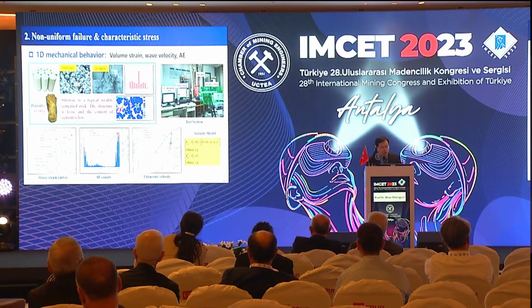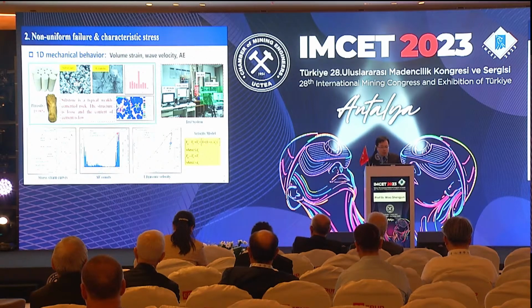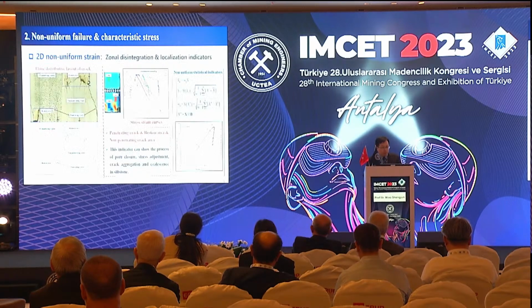In the uniaxial compression test, we found that the volumetric expansion stress of the siltstone is only 44% of the UCS, which is obviously lower than the 80% observed in dense and hard rock, such as granite, marble, and sandstone. And then we studied two-dimensional apparent non-uniform strain of siltstone.